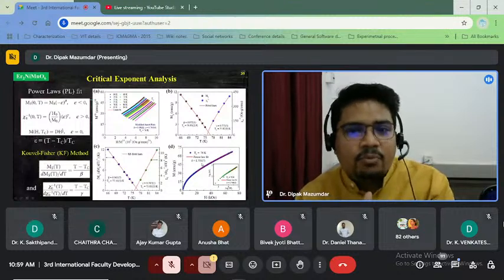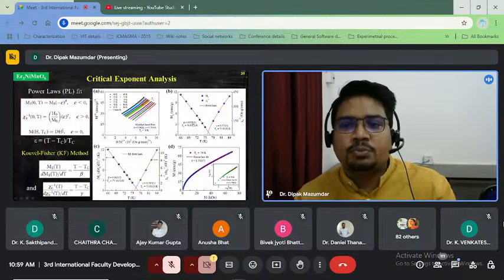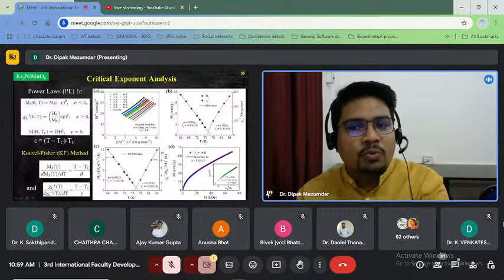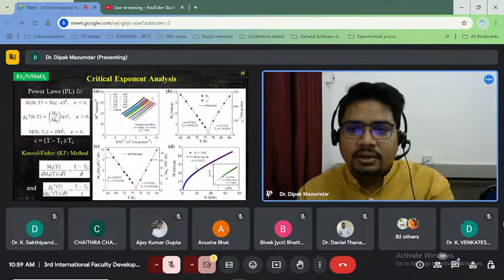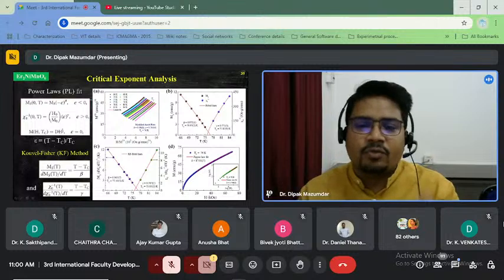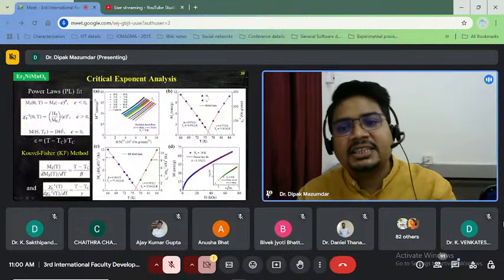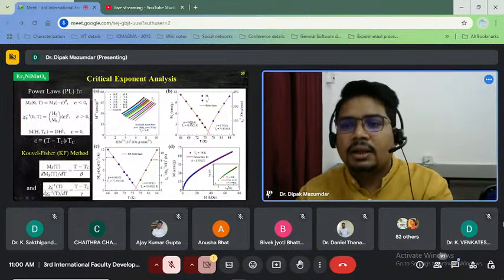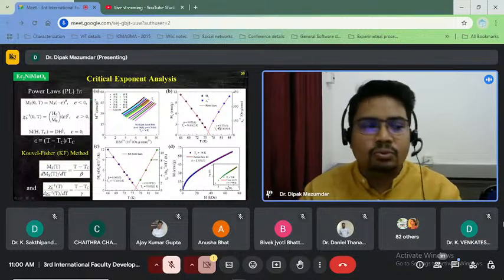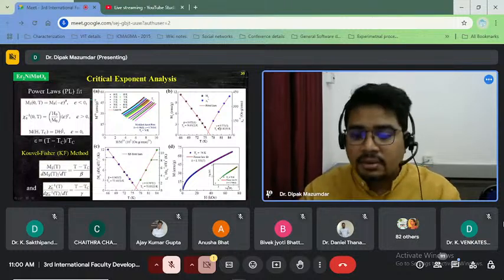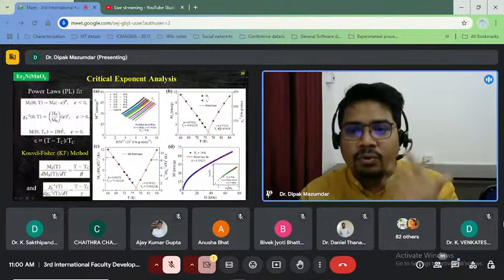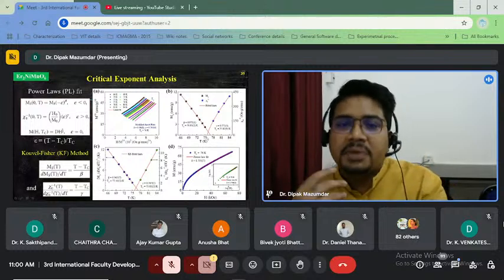For a mean field model, the value of beta should be 0.5, gamma should be 1, and delta should be 3. But everything is deviated from the ideal value, where beta is close to 1 and gamma is decreasing to 0.5. Why did this happen? This should not be expected for a universal magnetic behavior.